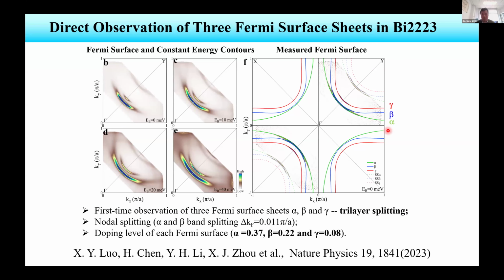Then we measured the Fermi surface of this bismuth 2223, and from the constant energy contours at different binding energies, we can clearly identify three Fermi surface sheets. We call them alpha, beta, and gamma. This is the first time that people observe three Fermi surface sheets in bismuth 2223. I think it's mainly because it's heavily overdoped. The doping levels are: alpha 0.37, beta 0.22, and gamma 0.08. So alpha and beta are heavily overdoped, but the gamma Fermi surface is heavily underdoped. So we have three Fermi surface sheets observed.